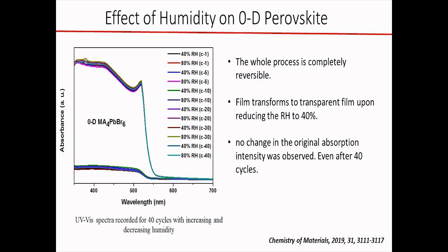We could go back with the humidity from 40% to 80% and measure so many cycles, and the process can be completely transformed into one another. That means the 0-dimensional perovskite changes to the 3-dimensional and back and forth.